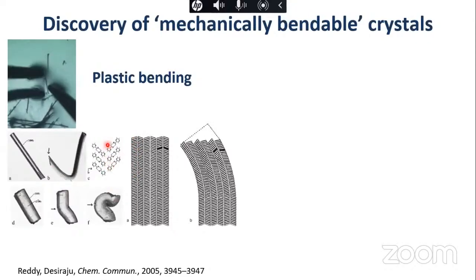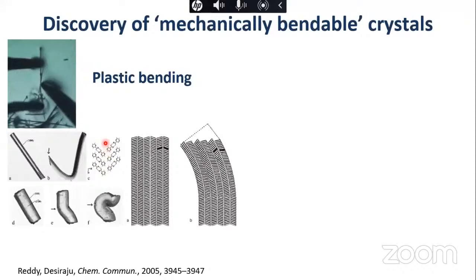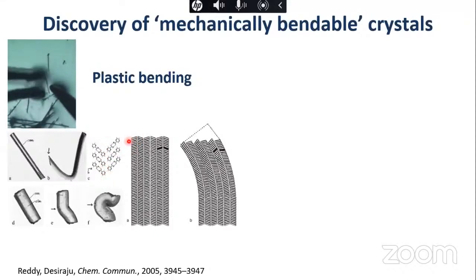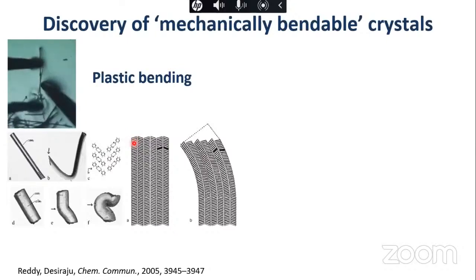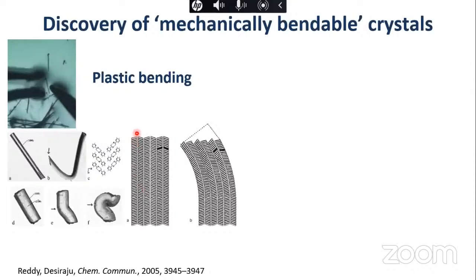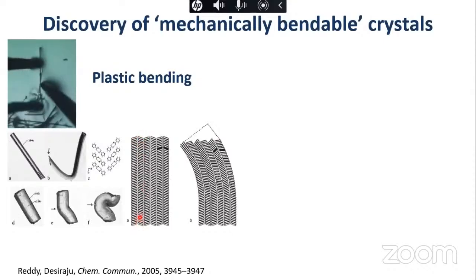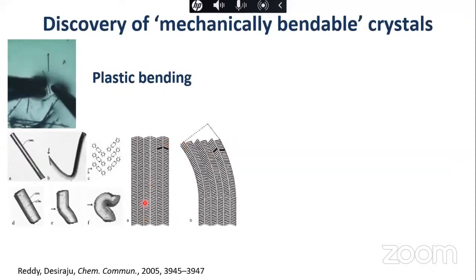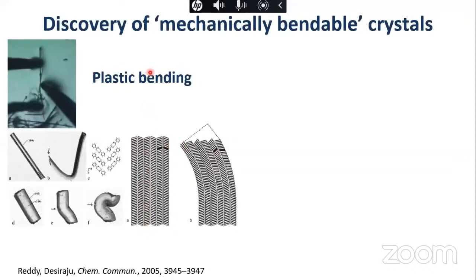For example, if you see here, these are CH groups actually. So these are van der Waals type of groups, and then you have weak interactions. And then these are your aromatic groups, which stack one over the other. And then between these stacks you have weak interactions. So when you push the crystal from this side. For example, this is the long axis of the crystal.